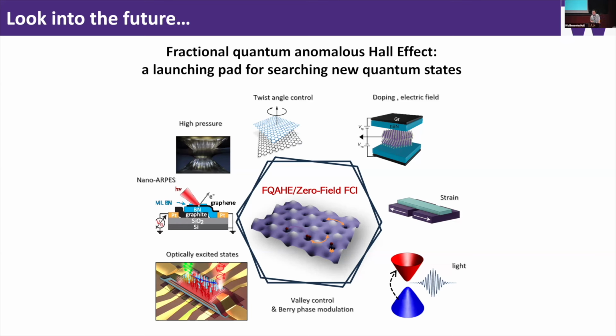In both the local data and the SQUID data, it seems there's always a dip below what, what's that? That's the 4/9 state. Yeah, it's a state. In the MIM, in the SQUID, and also in all the recent optical measurements, we see it. So I think it's a robust state. The reason, as I highlighted in red font in my first lecture, is that we haven't seen the quantized anomalous Hall yet. But other than that, I'd say probably it is another FCI state.